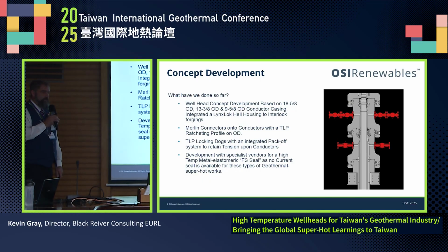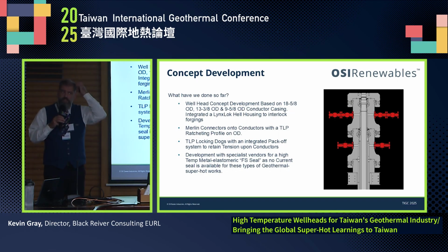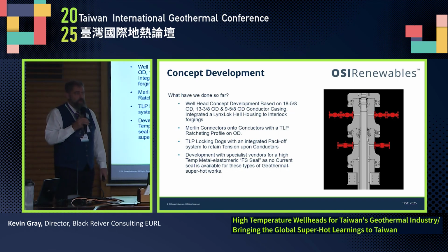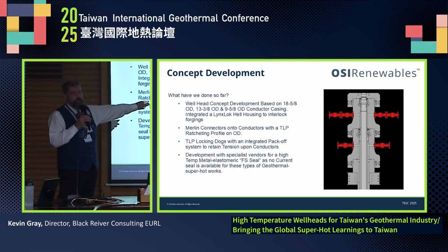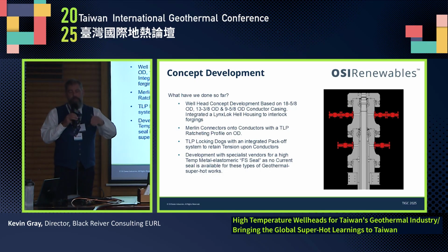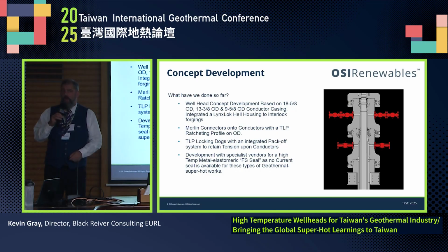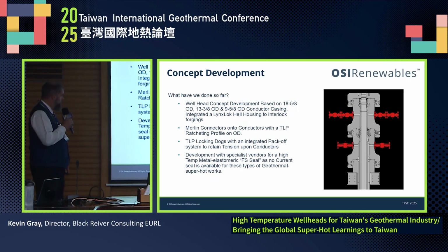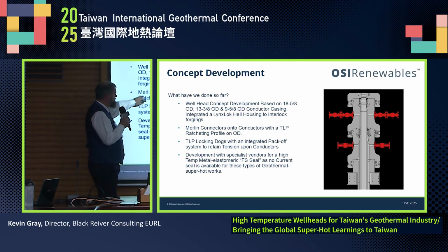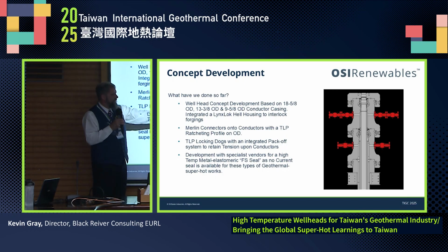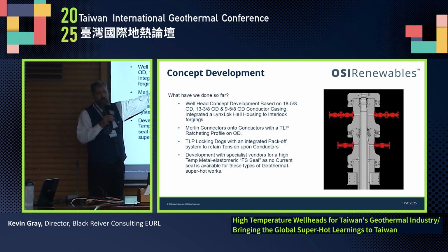So is this all pie in the sky? Is this all a fantasy? No, we're actually under test right now. We have tested the metal-to-metal seals that we intend to use here, and even if you don't want the full LynxLok system, the metal-to-metal seal technology is now 400 degrees, so we can give you a wellhead that will function at 400 degrees C.